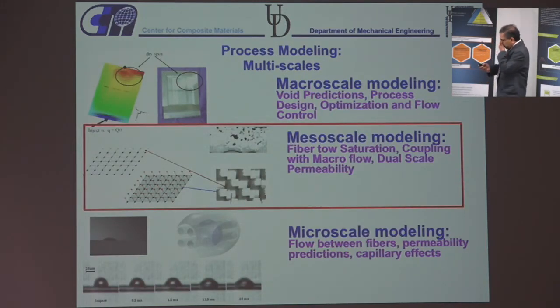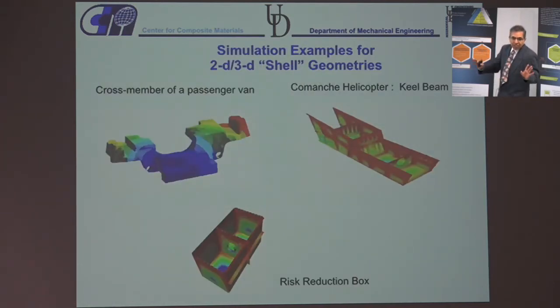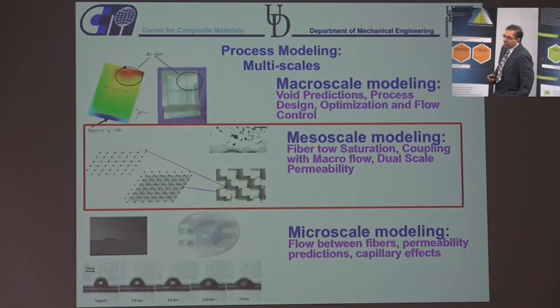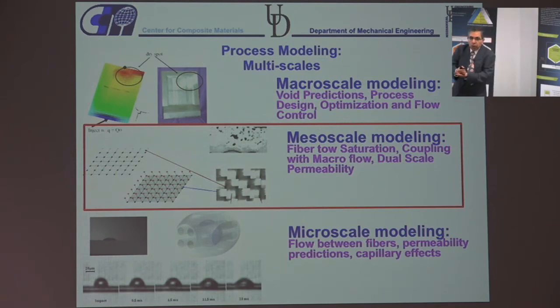So at this point I should have said, okay, work done, let's stop working in this area, move on to the next area, but there were still problems. The one nice thing about working in a center is that the industry comes in and tells you what their problems are. As an academician, you try to think about how to address that, because that's the challenge, right? Here, the problems are, they're saying, okay, you can do the dry spots, but when we take a micrograph of the part, we see that we still have porosity inside, between the tows or inside the tows. What that told us is that really we need to model this as a dual scale porous media. The resin comes in faster in between the tows, and then it's impregnating the tows.